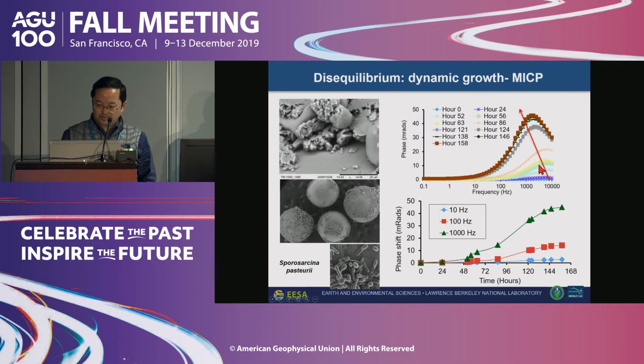And we also do this in a biotic condition. This is microbially induced calcite precipitation that has very different mineral morphology. You do see very similar behavior, again an increase of the magnitude and a shift of the peak from higher to lower frequency over time. So this basically shows a very high signal from the disequilibrium condition during calcite precipitation.